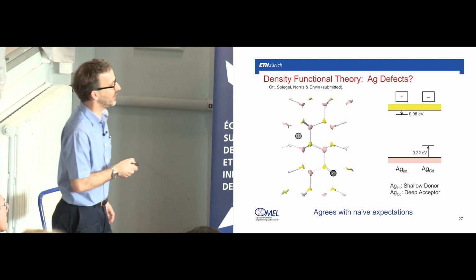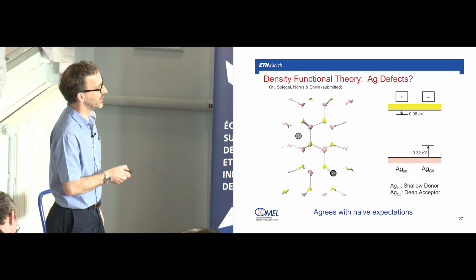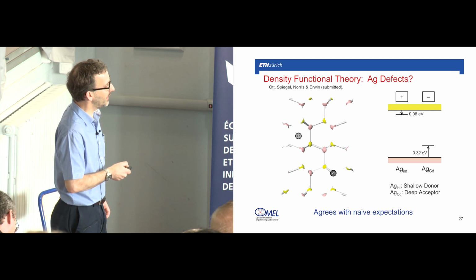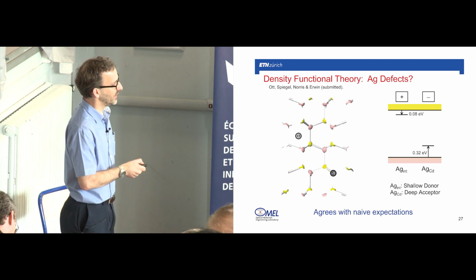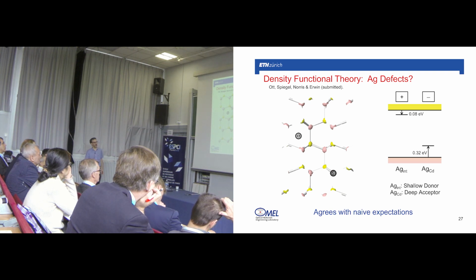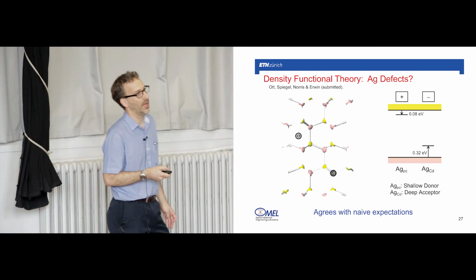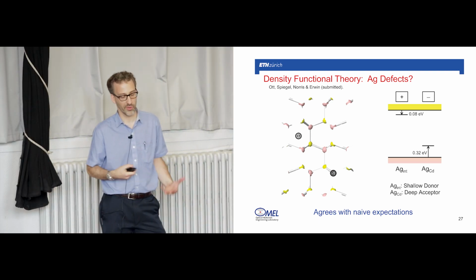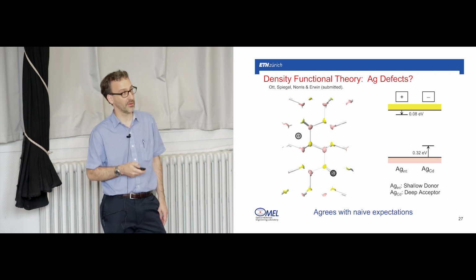And then for the substitutional, it was a deep acceptor. And again, if the Fermi level is mid-gap, an electron will fall into it, and it'll become negatively charged. And all of this is kind of consistent with what we would expect. So we thought the interstitial would be a donor, and this also agrees with old bulk literature data for silver in bulk cadmium selenide.